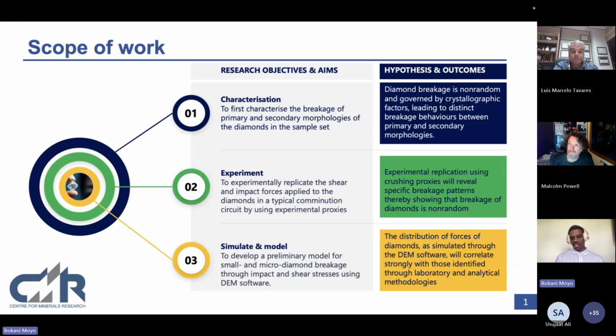My work can be broken down into three phases: the first being characterization, the second being experiment, and the third being simulation and model. Under the characterization phase, the research objective is to first characterize the breakage of the primary and secondary morphologies of the diamonds in the sample set. Under experiment, the objective is to experimentally replicate the shear and impact forces applied to the diamonds in a typical comminution circuit by using experimental proxies. Lastly, we want to develop a preliminary model for small and micro diamond breakage through impact and shear stresses using DEM software. The first hypothesis linked to the characterization of the sample is that diamond breakage is non-random and governed by crystallographic factors, leading to distinct breakage behaviors between primary and secondary morphologies.